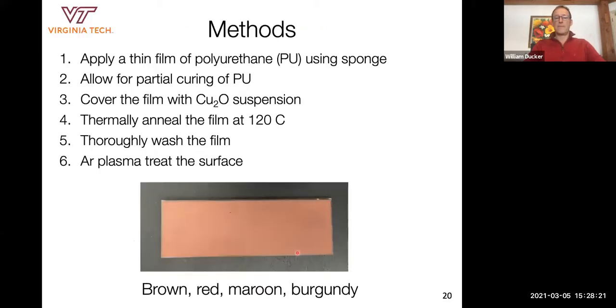So the way we did that was we applied a thin layer of polyurethane onto a surface using a sponge. We allowed it to partially cure, and then we covered the film with a cuprous oxide suspension and ethanol. The ethanol was to suspend the cuprous oxide, but also it softens the polyurethane and allows polymer migration. We end up with a coating that looks like this. To my eye, it's red or brown, but many people in Virginia Tech think this looks maroon or burgundy. I'm not really sure. I guess the color is in the eye of the beholder.